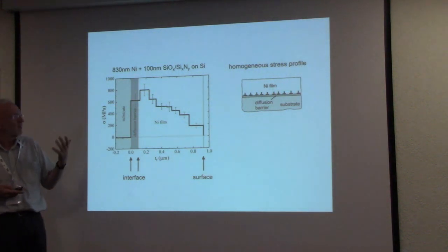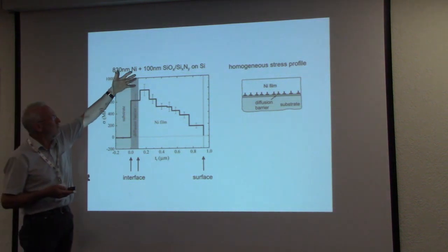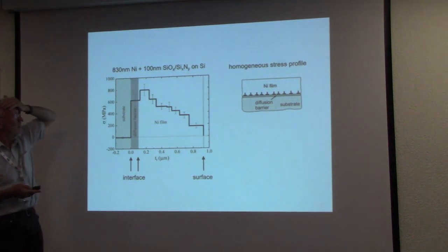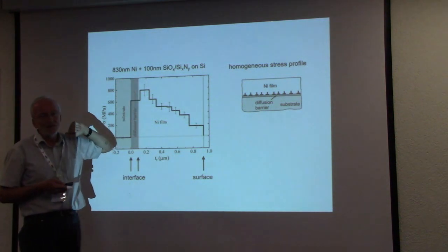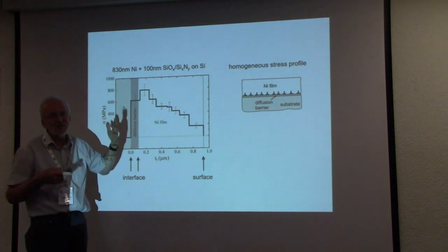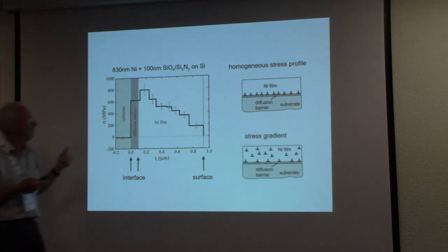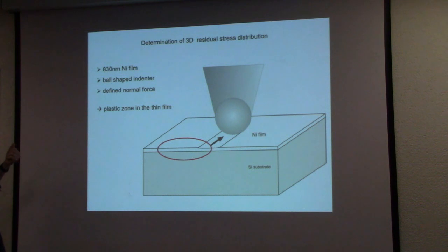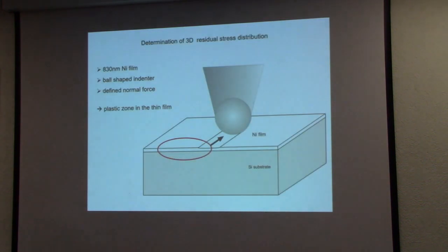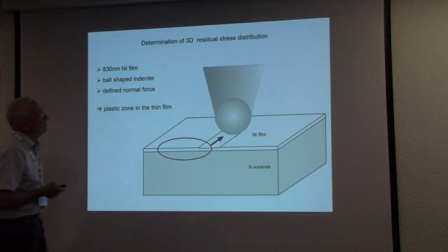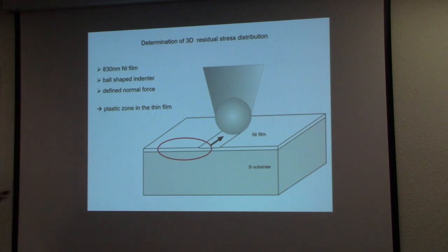If you then try to calculate, for example, interface toughness, you have to take into account this gradient in the residual stress. In addition, that makes this consideration more difficult. But this technique can also be used to determine the 3D distribution of residual stresses.